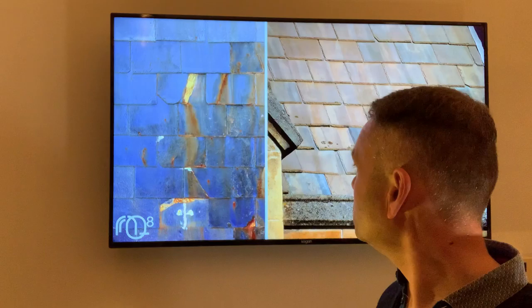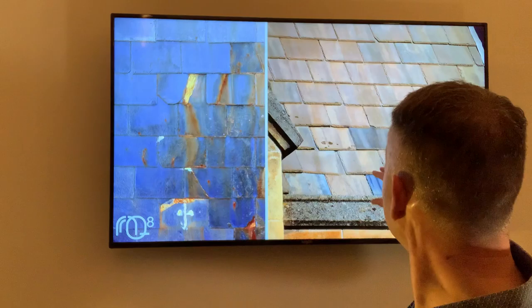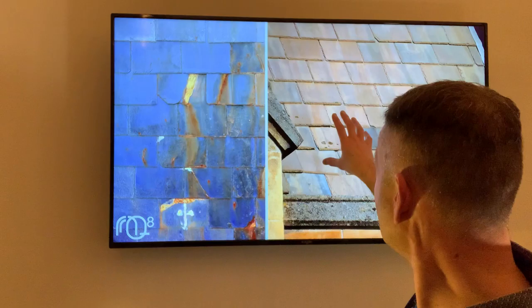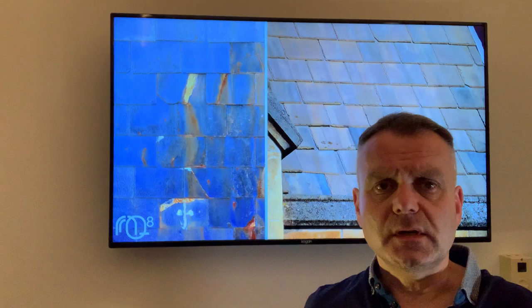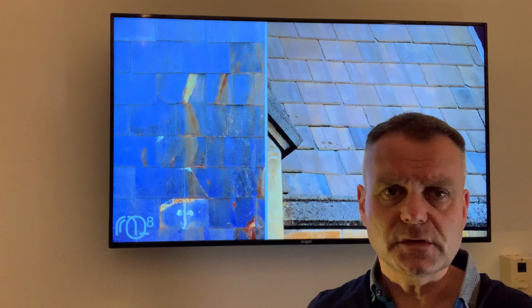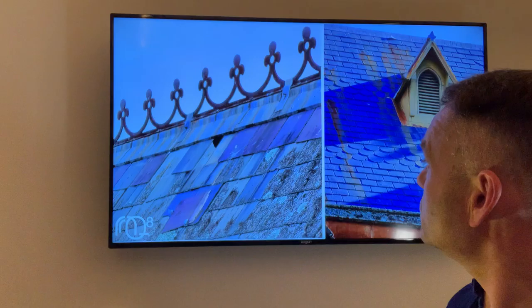This roof basically needs to be replaced as a matter of urgency and is being poorly maintained. The image on the right shows a historic property in North Adelaide where a whole variety of different slates have been used, many appearing to be Willunga slate. Willunga is the local South Australian slate and is very difficult to assess for degradation because it tends to delaminate underneath the top surface. It doesn't have a life expectancy of more than about 50 years.